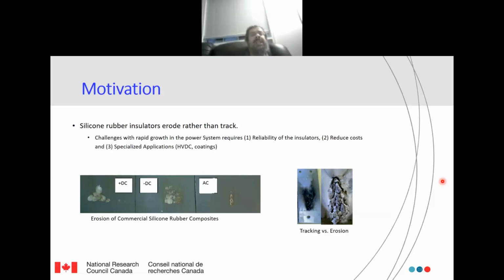One of the reasons for using silicone rubber, a non-carbon based polymer, is to avoid this carbonization or tracking. However, because of certain mechanisms, maybe Dr. Muhammad will talk about it, tracking can still happen, but erosion is the main thing that happens in silicone rubber. The material just erodes from the surface without tracking, and mainly we were testing the erosion ability of silicone rubber. Next, please.